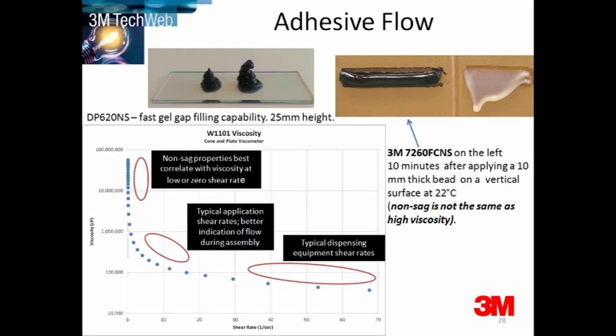This interesting slide shows the effects of adhesive viscosity or adhesive flow. There is a balance to be had between getting good flow and wetting, and also having practical physical characteristics to make the adhesive easy to apply in the real world. This shows the effects of viscosity, non-sag, and gap fill properties, which are interrelated. Viscosity governs the ease of flow of an adhesive. With most adhesives, the viscosity is shear-rate dependent.